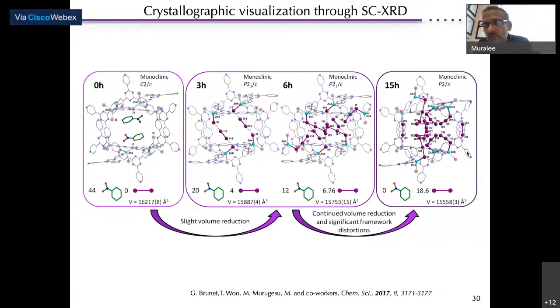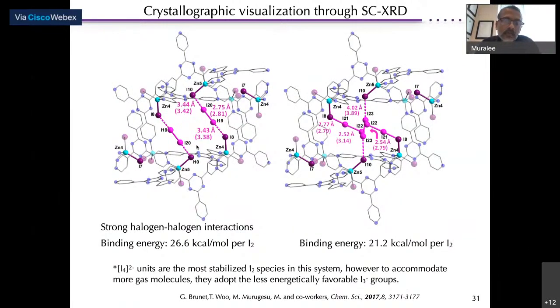We tried to collect after 20 hours, and we lost crystallinity completely at that point. And unfortunately, we couldn't go back either. And furthermore, we wanted to do calculations to make sure that what we are seeing is correct. Through computational methodology, we were able to find the binding energies. So strong halogen-halogen interaction is seen here.